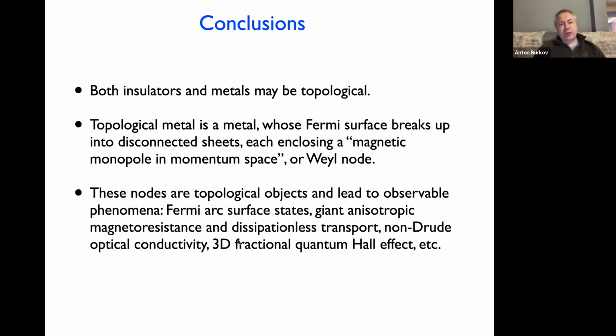There is giant anisotropic magnetoresistance, which I talked about, and a new dissipationless conduction channel, non-Drude optical conductivity with an extra peak on top of the Drude peak, whose width is proportional to the chirality relaxation rate and height proportional to the square of the magnetic field. And also in topological metals with strong interactions, there can be very exotic phenomena like a three-dimensional generalization of the fractional quantum Hall effect. Okay, thank you.